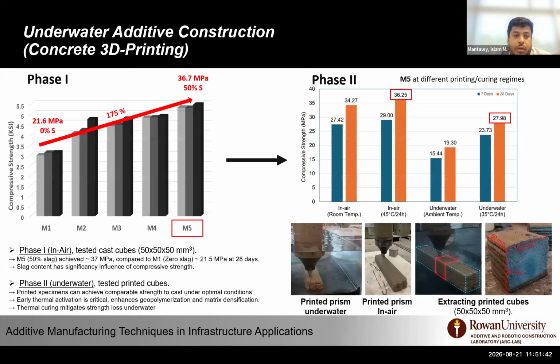We also did a lot of mechanical testing, compressive strength for the cast version of the material and the printed version of the material, and you can clearly see the decrease in strength when printing underwater.